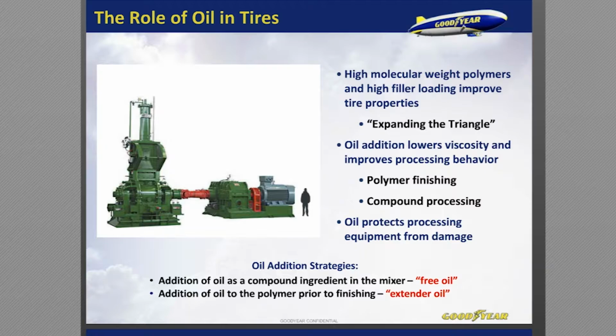So when we add oil just as an ingredient to a compound mix where we're adding filler and different rubbers and other additives, we'll add oil directly to the mixer. We consider that free oil. And then we will add oil to either polymer cement in the case of solution polymers, or to latex in the case of emulsion polymers, prior to finishing. So basically for solution polymers, it's where the solvent is removed, and that is called extender oil.